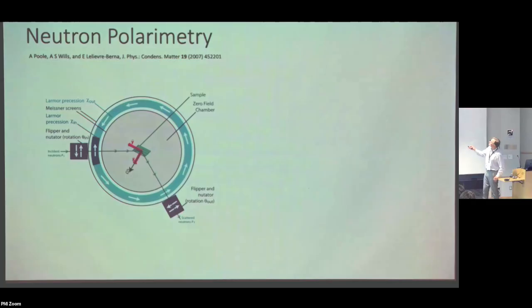related technique that's called neutron polarimetry, which I won't be able to fully describe, but it involves measuring for each Bragg peak, actually, determining the transfer matrix that transfers the incident neutron spin state to the final neutron spin state. So neutron comes in, it diffracts, but that actually rotates the spin state to some other orientation, and then it leaves the sample. And so in this case, the experiment is done inside a superconducting shield. So this is really in a zero field regime. And then the neutron is extracted from that, and you measure the full kind of transfer matrix.